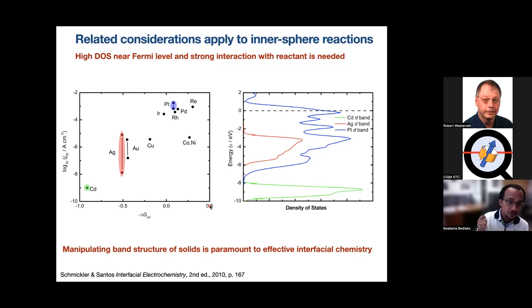the band, and do you have a strong enough interaction, but not too strong an interaction, with the reactant, let's say a proton in solution or hydrogen ion. And what you find is that you can actually correlate the activity of various transition metal surfaces to whether or not their Fermi level crosses this large density of states d band. All right. And without going into any more detail than that, the point I'm trying to drive home here is the idea that manipulating band structure of solids is paramount to designing and engineering interfacial chemistry.